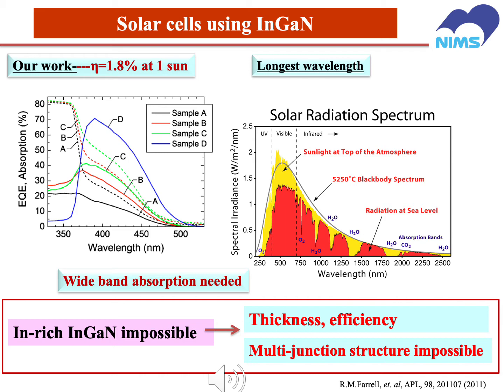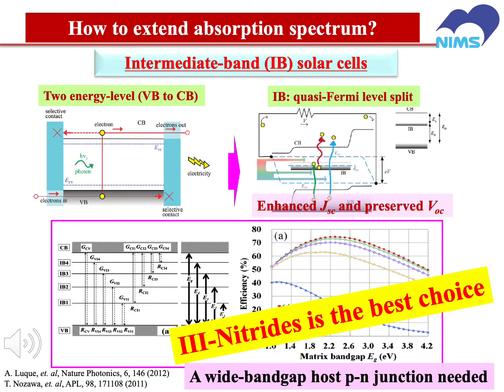So this is because the absorption region of the InGaN solar cell is still focused on the shorter wavelengths, and this is the longest wavelength absorption for the InGaN solar cell. We can see that compared to the solar spectrum, it still cannot reach the highest absorption in the sunlight. So to improve the conversion efficiency of the InGaN solar cell, it is very necessary to enlarge the absorption band. This requires the indium-rich gallium nitride, which has indium composition at around 40%. But this also leads to a lot of difficulty, as I introduced before. So how to extend the absorption spectra without increasing the indium composition?